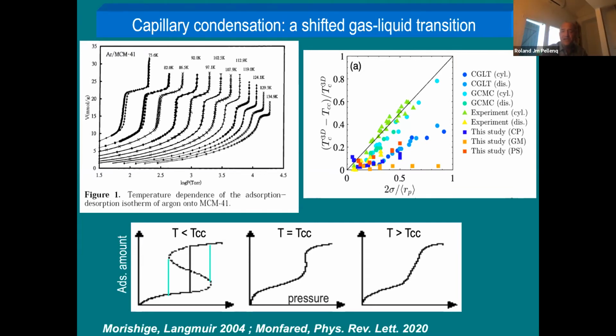And what's interesting in this work, besides all the points that you can see, is that we have this linear behavior of the shift critical point with 1/r, the pore size. Sigma is the molecular diameter.